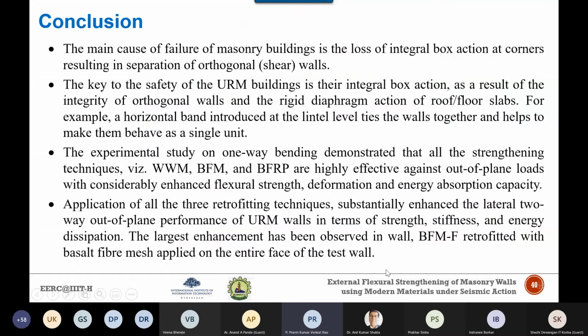So the main conclusion is, if you have any existing building and you want to strengthen or retrofit it, then we can use composite materials like wire mesh, textile reinforced mortar, and fiber reinforced polymer very effectively, where not only is there a strength enhancement, there is a large ductility and also a large energy absorption capacity. Secondly, whether you test the masonry walls in one-way bending or two-way bending, there will be a significant enhancement. The two-way bending represents a realistic picture of the boundary conditions.